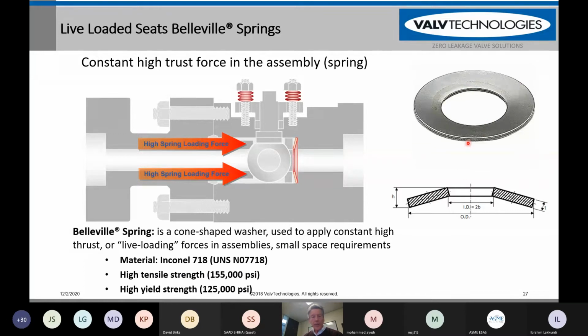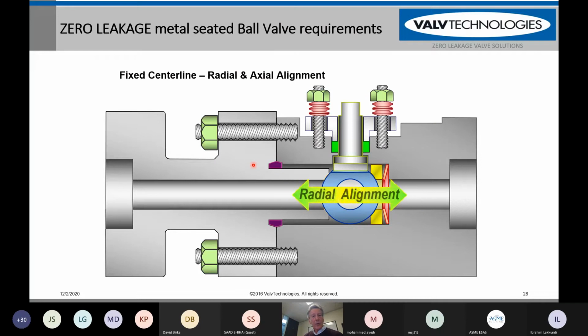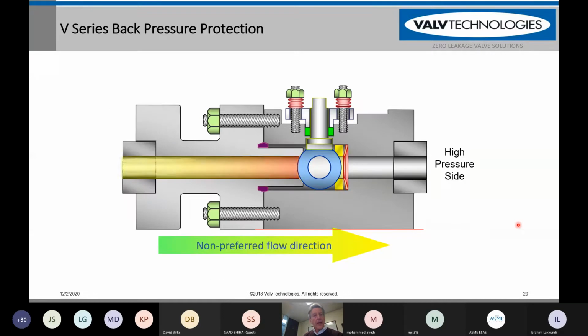It's an extremely strong, extremely durable spring that we utilize, and it has upwards of 155,000 PSI tensile strength, which is very, very high. For instance, if it was made out of 316 stainless steel, it'd be somewhere about 35,000 PSI. So it's very, very strong, and you can see when we load it, it puts a load on the ball and the seats, and this is kept in constant tension. We always have complete radial and axial alignment of our ball. We hold very, very tight tolerances for all of our valves. And you can see even in the reverse flow, we have bubble tight leakage.